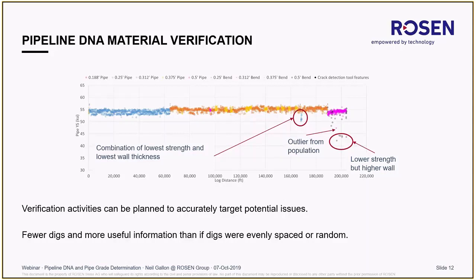When you take that PGS measured yield strength and integrate it with the other information, we were able to tell that not only was that lower strength, it also had higher wall thickness. Therefore, it isn't as great an integrity threat, because although the actual yield stress is going to be lower, because the wall thickness is higher, the load bearing capacity is probably going to be equivalent.